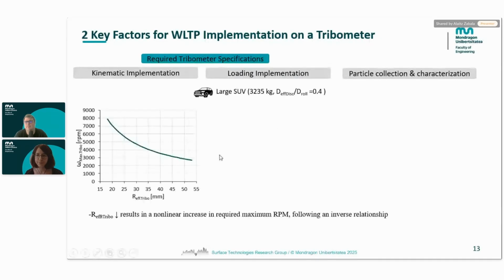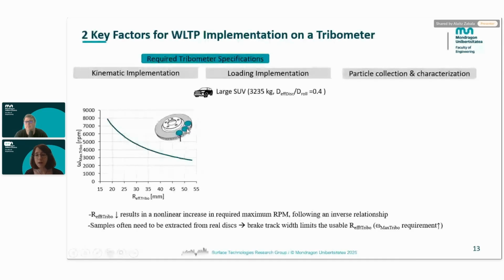Once we have had a look at the key factors of the kinematic and loading implementation, I would like to provide an overview of the required tribometer specifications if we would like to reproduce the WLTP. In order to do so, we selected a large SUV vehicle as a heavy vehicle. Here we have the rotational maximum speed required in the tribometer, depending on the effective radius selected. As we can see, if we select a small radius, as the radius is decreasing, the maximum RPMs are increasing in a non-linear way. It should be considered that many times the miniaturized samples should be extracted directly from the real disk, which means that the usable radiuses could be small, so that the maximum RPMs required could reach up to 8,000.